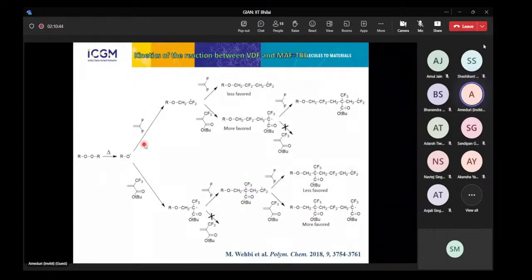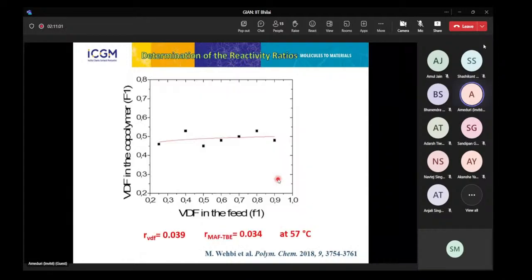So this could be understood by the different reactivity of all of them. As you know, MAF does not homopolymerize, okay? So it cannot go through propagation, but you have a cross propagation. And here it was favored with a cross propagation again because of this alternance between MAF and VDF. And we measured, of course, the reactivity ratio. So you can see that they are very low. The product is about 10⁻³, showing that it's alternating.